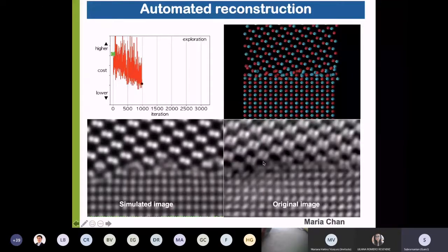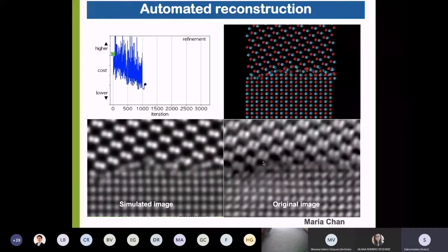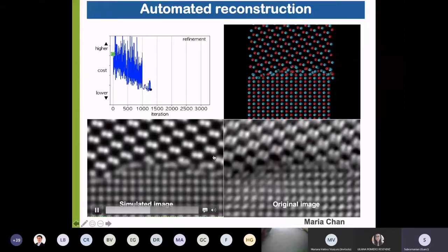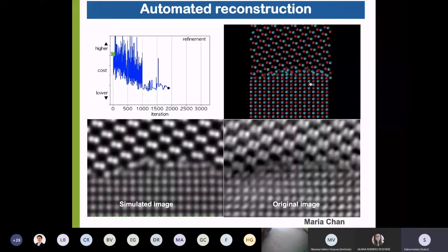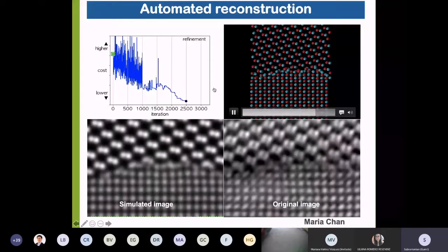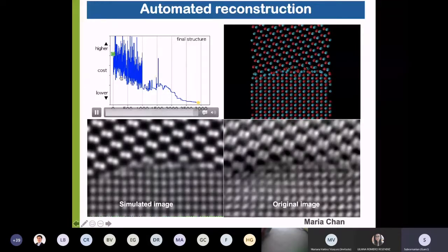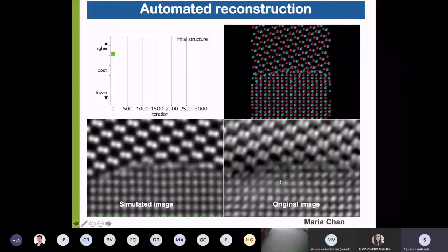But in addition to just looking at an interface matching or pattern matching, what one can do is to actually use information from the physics of the interface. So you have an MD model that is also giving you information on the energetics, and so the cost function now includes the most energetically favorable interface as well as the best match to the low resolution TEM. So once you actually have this optimization done, you have now a complete visualization of the actual interface that is the most physically viable as well as the best match to your low resolution image. And this is basically a very powerful technique to automatically reconstruct images from microscopy.